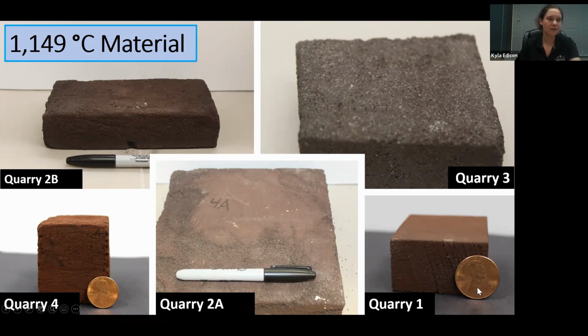When this project was first started, we used material from Quarry 1 here, this small sample here. It was used in collaboration with SwampWorks as a static launch pad test. It was the only basalt that was used at the time. Funnily enough, it was also kind of the best. They hadn't tested anything else, so it's kind of funny that it is actually our best material. It sinters really well. When they did the test, the launch pad itself, the design of the tiles flew all over the place, but the tiles themselves weren't heavily damaged, and they kind of came away unscathed.